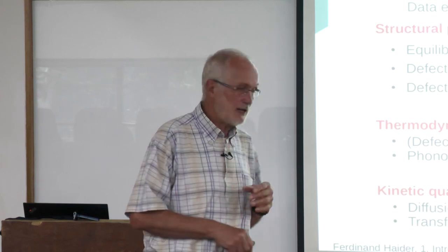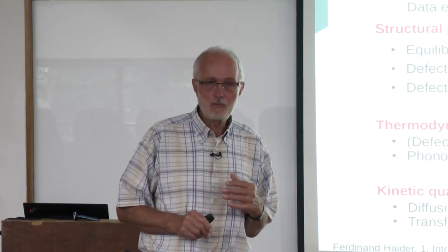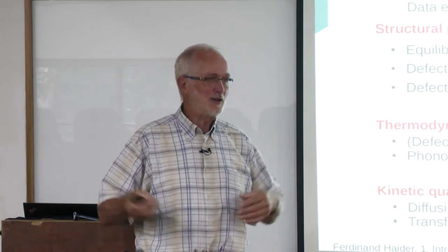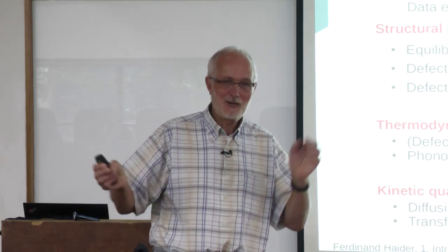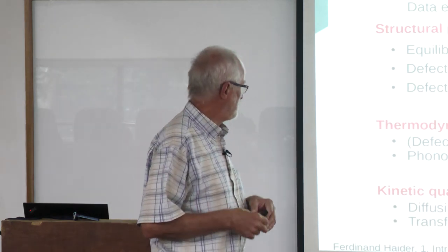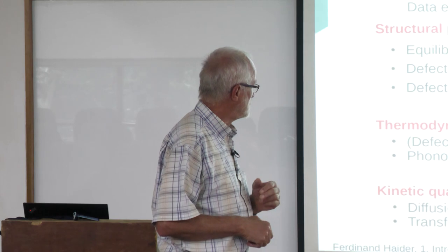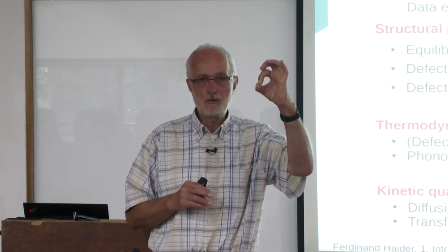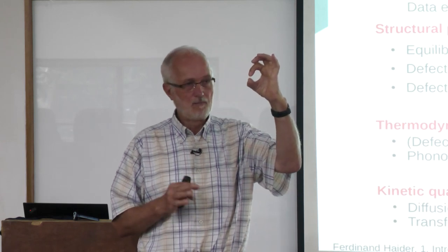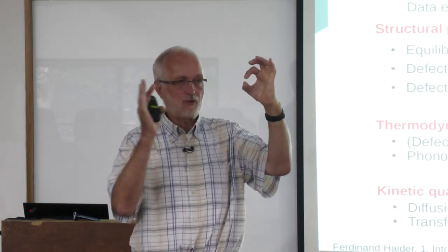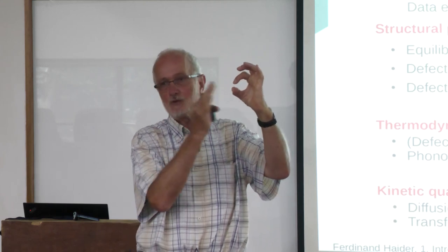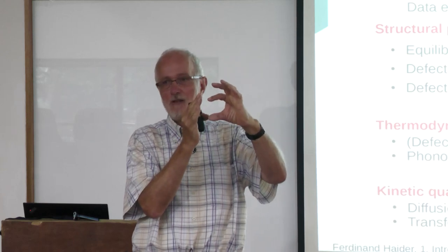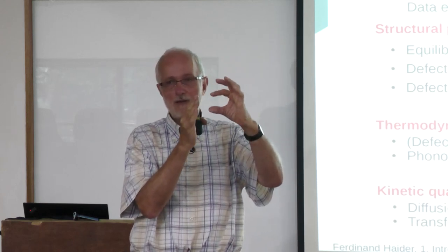Closely related to this are the vibrational entropies. If the atoms start to vibrate, you create some kind of disorder, and disorder is more or less equivalent to entropy. So this also contributes to free energies. Very important also, for example, if you consider a vacancy, this will probably change the vibration spectrum of atoms around it. So the vacancy has a particular energy, but also a particular entropy.